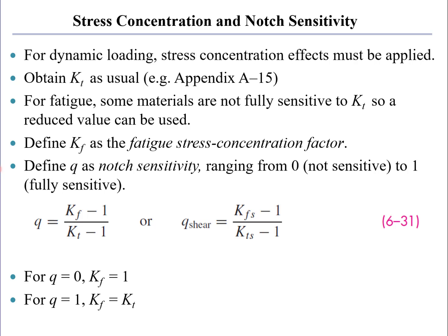In effect, what we do is we knock down the stress concentration factor. So we start at first with an elastic stress concentration factor for the given stress concentrator. And then we note that for some materials, they are not fully sensitive to the elastic stress concentration factor. So we have to knock that factor down to an effective fatigue stress concentration factor using something called the notch sensitivity. So the notch sensitivity provides this ratio of the fractional portion of the stress concentration factor. So this is the fractional portion of the fatigue stress concentration factor divided by that fractional portion of the elastic